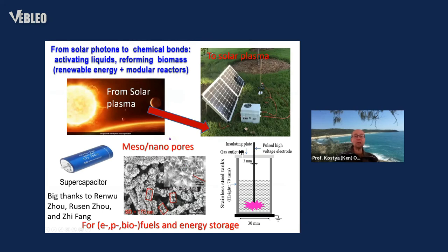A very important thing is to use renewable energy in this treatment. And one of the most exciting ways is to use what we can even call solar plasma. But it's not plasma in the sun, which has millions of degrees temperature, but it is our low temperature plasma that we generate using solar panels, capture solar light and use voltage converters to generate high power plasma discharges at atmospheric pressure, such as spark discharges, in the air or even in solutions where we can put a lot of precursors, as I will show you in several examples, and we can produce solid and liquid materials and then apply them. For example, use the solid materials with specifically customized pores in energy storage materials, such as supercapacitors. So a lot more examples will follow.